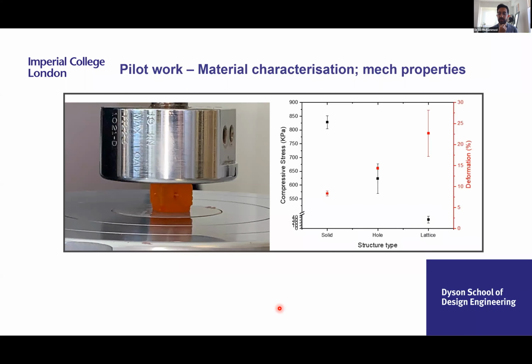Next, we looked at the material characterization of the mechanical properties. So here, as you can see, when we go from solid to lattice, you get lower compressive stress at failure. However, the deformation increases, and this makes sense because with a lattice, you obviously have more air, more space. So the material is essentially softer without intrinsically being softer. So that means it can handle a higher compression before failing.